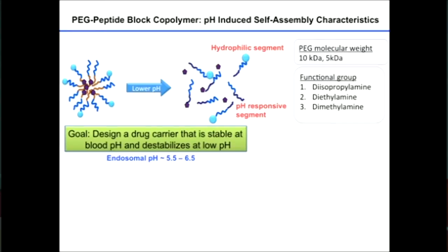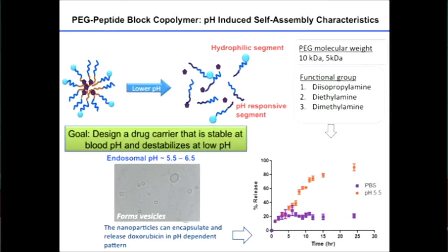So in designing these pH-responsive systems, we decided to stick with the polypeptide because it's biocompatible and begin to attach different amine groups to them. Amines are basic groups. They buffer at a range of different pHs. And when they begin to buffer, they become positively charged and they become water-soluble. When we began to work with this design, and I won't show you the chemistry in this case to keep everything simple, we found that they actually form vesicles, much like liposomes. So we had these vesicular structures, and we found that they essentially do fall apart at low pH.